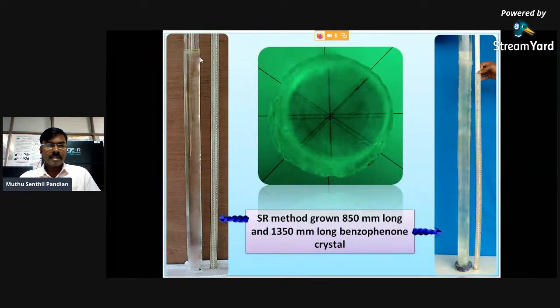So this is the 850 mm long benzophenone crystal. This is the 1350 mm long benzophenone organic single crystal for nonlinear optical application. This is the double diffraction pattern of this benzophenone single crystal. The total thickness of this crystal is 5 centimeter.